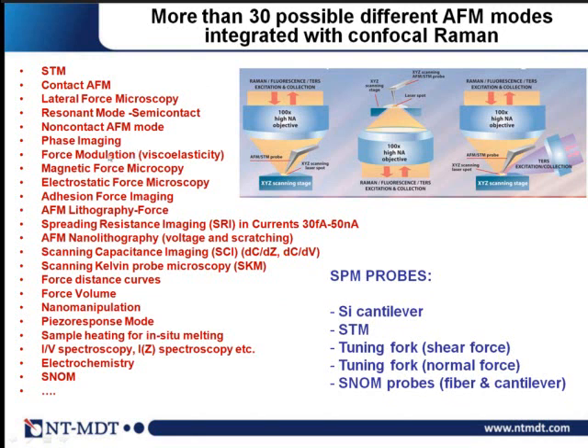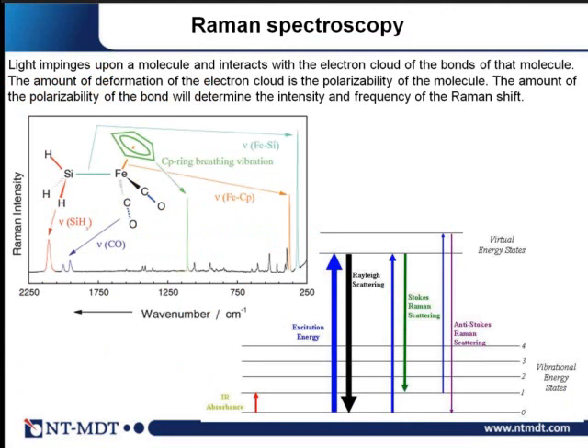AFM modes provide information about capacitance, surface potential, local resistance, adhesion forces, electrostatic forces, magnetic forces, and so on. Every physical property of the surface can be studied by atomic force microscope with very high spatial resolution. What is typically missing in AFM is chemical specificity of the obtained maps. To get chemical information about the surface composition and nanostructure composition, we need to apply optical microscopy and spectroscopy techniques.